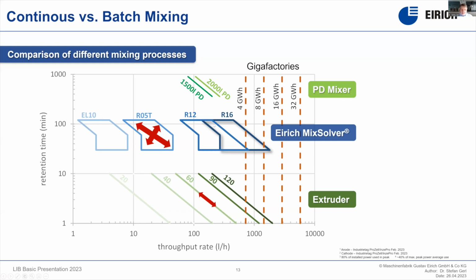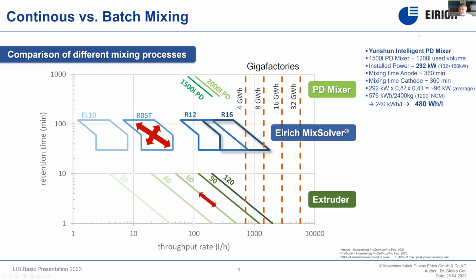A typical plant with 1 R12 mixer comes into the range of 3 to 4 gigawatt hour. This means if we want to design a plant with up to 10, 12, 16 gigawatt hour, we just put 3 or 4 machines in parallel. And if we have a view onto the energy consumption, you can see that there's a big difference, and this is at the end the cost saving.